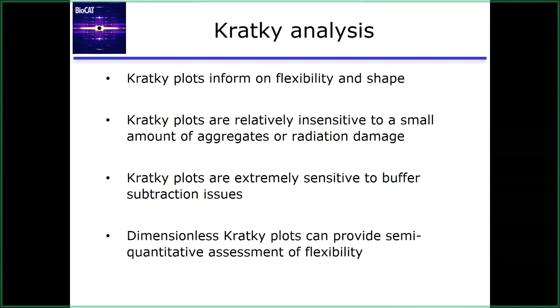However, dimensionless Kratky plots are extremely sensitive to low Q issues because they rely on knowing RG and I0 accurately. Kratky plots are also extremely sensitive to buffer subtraction issues, so you can use them to assess buffer subtraction. If you're expecting something very rigid and it doesn't go back down, it can tell you that maybe you have a buffer subtraction problem. But this is a good way to get a feel for what you're looking at in the solution.